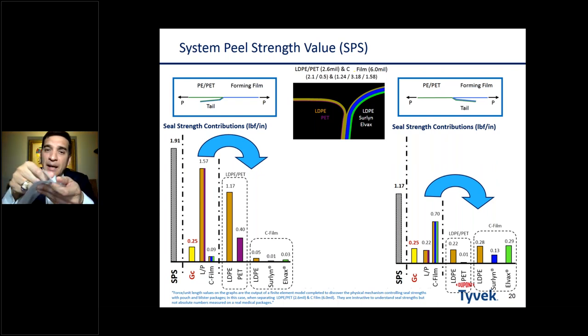But when I turn it around the other way and pull this way, I'm not deforming the LDPE on that side, not as much, very little. I'm not deforming the polyester. So I'm not getting that much of an energy contribution. You can see in this example we're using a forming film, and even the forming film is not contributing greatly to the value that we are seeing on the instrument. So, very important point here: when we do peel strength data, we're not only measuring the seal integrity, but also the deformation of the different materials involved in the entire package.